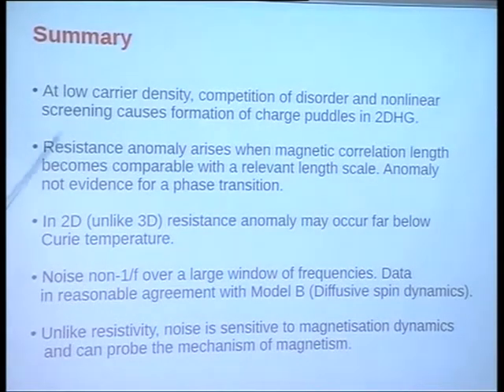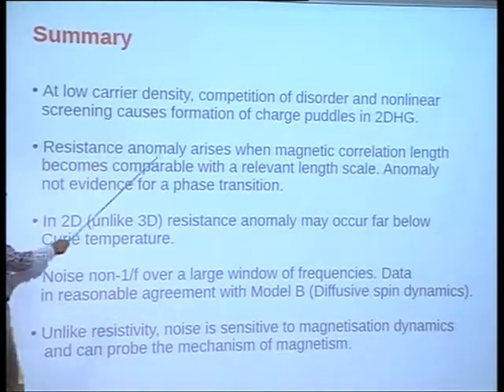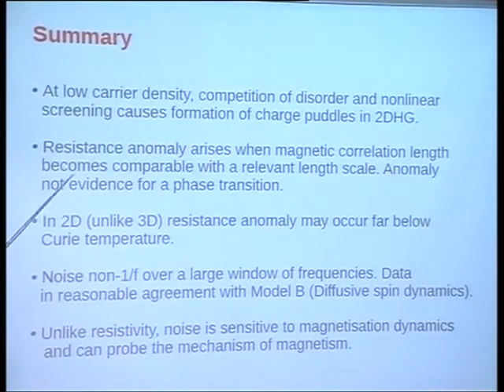So here's the summary of my talk. I showed how at low carrier density you can have competition of disorder and nonlinear screening, which can cause formation of charge puddles in the quantum well. And I showed you how the resistance anomaly can arise when the magnetic correlation length becomes comparable with a relevant length scale, and it's not necessarily equal to the 2D transition temperature, the Curie temperature. In fact in 2D we never have a phase transition, yet we see an anomaly.